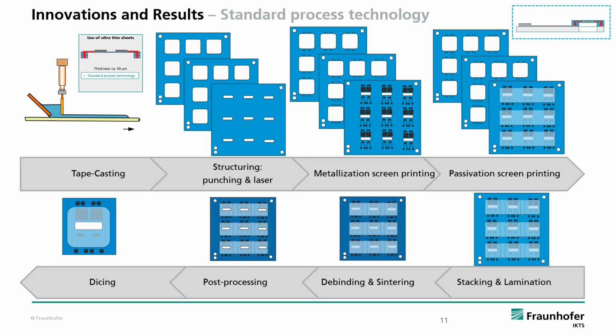The electrical circuits, in this case temperature sensors and heaters, are screen printed on the tapes. Vias are filled in mask printing to get the vertical electrical connections. The active metallization parts are passivated, again in a screen printing process. Next, all layers are stacked and laminated together. While sintering in an oven, the organics burn away and the glass ceramic gets densified. An optional laser process reopens the cutout. At last, the ceramic wafer is diced to separate all sensors.